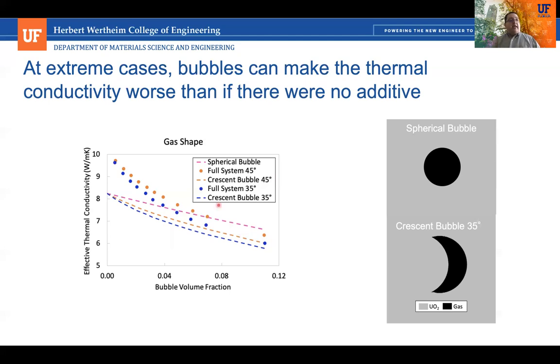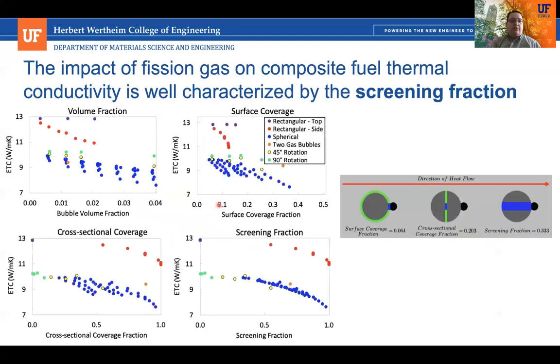So when we start getting fission gas around our particles, this can be a very large effect. And this is of course aimed specifically at dispersed particles, but this can be a big issue. So we need to understand this and be able to predict this behavior. So the next step is to try to come up with some metric that describes the geometry of our fission gas bubbles that has a good correlation with its effect on the thermal conductivity. So we looked at a number of different metrics, and we looked at the bubble volume fraction, which we already looked at. There's no clear distinction.